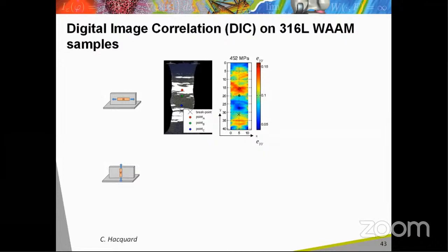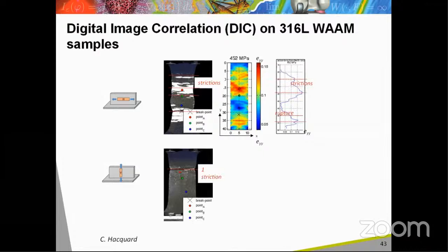microstructural heterogeneities. On the horizontal tensile specimens, an atypical behavior is observed that has not yet been explained, with several strictions in the sample. On the vertical specimen, the strain is mainly localized in the center of the successive layers, the interface between two layers being less strained, possibly due to a finer microstructure in the interface between two layers.